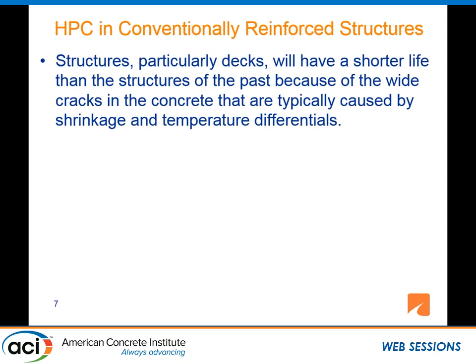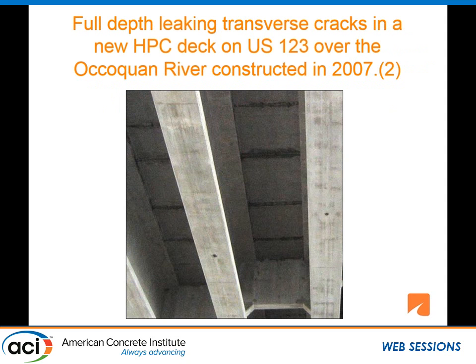However, with conventionally reinforced concrete structures, particularly bridge decks, which are flexural members, we're going to have a shorter life than many of the structures of the past because of the wide cracks in the concrete that are typically caused by shrinkage and temperature differentials. This is a picture of the underside of a bridge deck on US 123 over the Occoquan River, constructed in 2007. This is about 20 miles south of D.C.